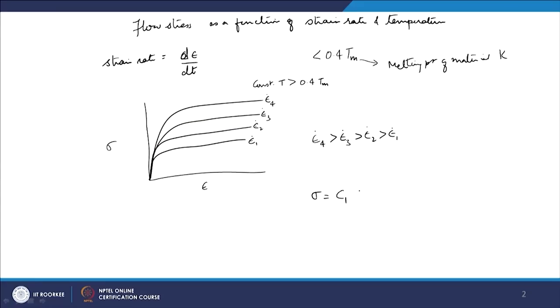relationship between stress and strain rate will be something like this. So, sigma equals C1 epsilon dot to the power m, at constant strain and temperature. So, already we have said that all the plots are at constant temperature. And constant strain means, suppose I just take a particular strain value here, and find out that for epsilon 1 dot what was the stress, sigma 1, sigma 2, sigma 3, sigma 4 and so on. Okay. So, they will follow a relationship like this, where m is the strain rate hardening exponent, or sometimes we call it the strain rate sensitivity index, that is, what is the sensitivity of stress to strain rate. Okay.